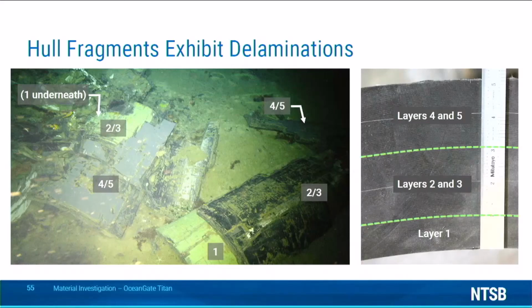So the delamination between the innermost shell and the middle shell occurred within the adhesive at the layer 1, layer 2 interface for all the pieces that could be examined. This was seen earlier on the single layer piece at the forward end of the hull, and it can be seen here for the layer that's labeled 1 at the lower right of the image. Another layer 1 piece is hidden on this image but is visible on the next slide. It too shows separation within the adhesive.